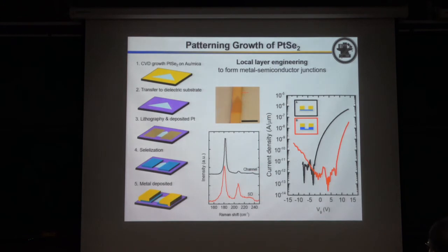Okay, so we also use this material to fabricate devices. We also try to do some local layer engineering. That means the monolayer in this material is very unique, because PtSe2 is a semiconductor when it only has one monolayer. But theory predicts that for 3 layers, this material becomes a semimetal. So this is very good to improve the contact, if you can engineer the thickness of the contact area.